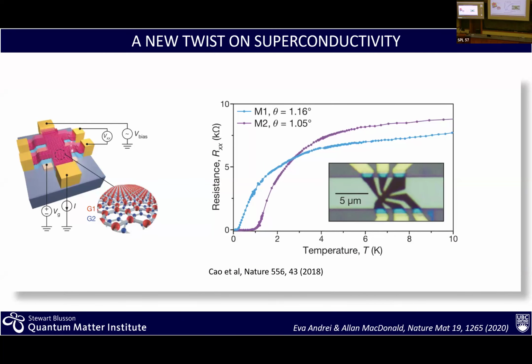And you can see that in the experiment. What Pablo's group has done is make devices out of the twisted bilayer graphene. Basically, you have contacts, you can bias the sample, you can measure currents. And here again, you see resistance versus temperature for one such device. Of course, these are exfoliated graphene, so they're small devices. 5 micron is the scale you see there. And what you can see is the resistance comes down, again metallic behavior, and then eventually goes superconducting. Interesting is to notice the difference between the 2 is a small change in the twist angle. So extreme sensitivity to the twist angle basically requires high precision in making it, but really allows you fine-tuning the superconducting properties. And again, graphene by itself would not be superconducting at all. So superconductivity really comes out of this deliberate stacking and twisting.